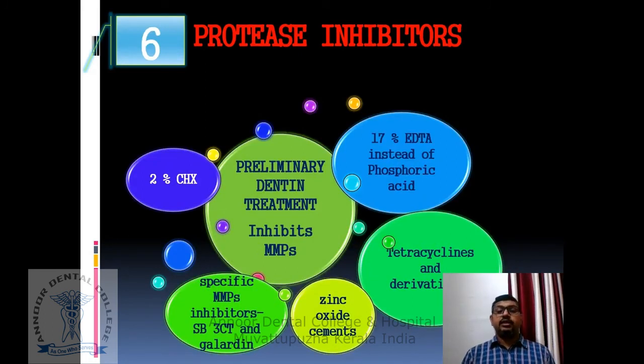Protease inhibitors. I told you initial bond strength might deteriorate over time. Why this deterioration happens over time is that you have a collagen mesh that is fully exposed, and all the mineral component has been lost. So it will activate the matrix metalloproteinases that are present inside the dentin. It will degenerate the collagen mesh. Bonding is with the collagen mesh, so if it degenerates, your bond strength also will deteriorate.